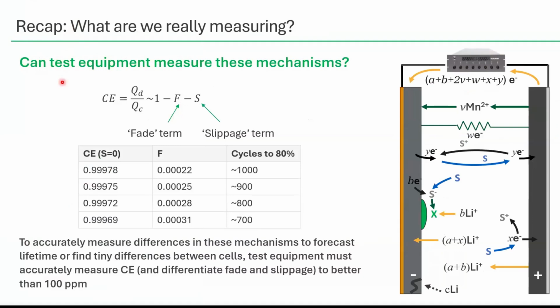Here I'm showing what this all really looks like when we go into the full picture. We like to talk about coulombic efficiency because all of these mechanisms affect it. We've got a couple different terms: one has to do with all those capacity fade mechanisms, and the other has to do with all these excess electrons we're counting during charge that act as self-discharge during the discharge step, which is that slippage term we discussed.